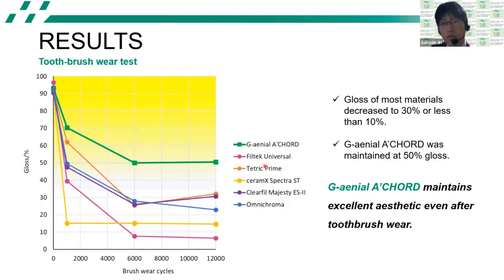Next, I show the result of the toothbrush wear test. The gloss of most materials except G-aenial A'CHORD decreased to 30% or less, or even 10%, after brushing 12,000 cycles. On the other hand, the gloss of G-aenial A'CHORD was maintained at 50%. This gloss value is higher than 40%, which is known to look glossy in the oral environment. This result indicates that G-aenial A'CHORD maintains excellent aesthetics even after toothbrush wear.